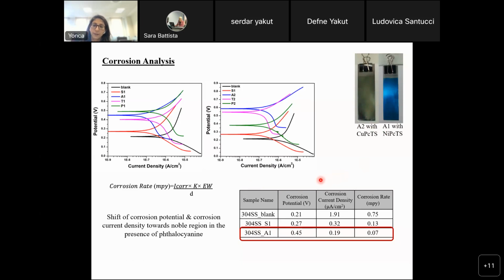As the phthalocyanines are introduced to the thin film structure, we have almost a tenfold decrease in the corrosion rate compared to the blank case. S1 again represents only the polyelectrolyte film, that doesn't have any phthalocyanine content. And also, once the nickel phthalocyanine is introduced to the system, there is almost a tenfold decrease in the corrosion current density.